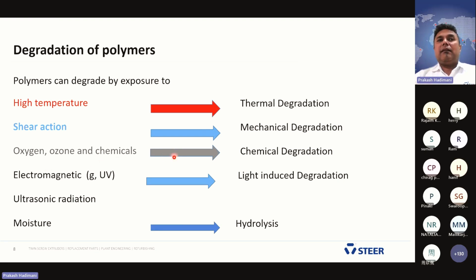Oxygen and ozone cause chemical degradation, when your polymer is exposed to oxygen. When you are feeding your ingredients with the polymer into the extruder, it takes oxygen along with the polymers. If it goes and melts inside the vessel, you lose its properties because chemical degradation is happening. It changes the color, sometimes yellow, and loses mechanical properties. And also chain scission, as we call it. To resist that, we need additives, stabilizers, and chemical resistance additives have to be used.